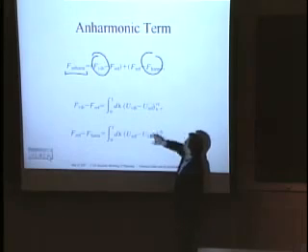While this one is very expensive because you need to calculate the internal energy with the quantum mechanical model, you are trying to sample the difference between two quantities that are as similar as possible, and, in the ideal case in which your classical potential is able to reproduce your quantum potential, this goes towards 0. So it's something that is very simple to integrate.